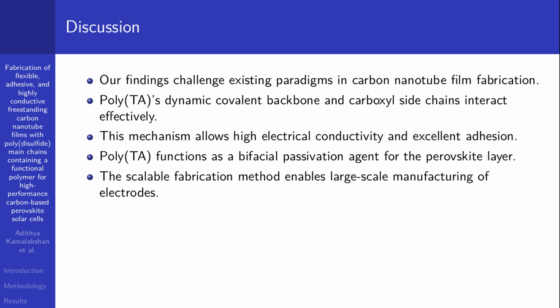synergistically. The hydrophobic backbone facilitates alignment of the carbon nanotubes, while the carboxyl groups provide strong non-covalent binding through interactions like hydrogen bonding, leading to a highly ordered, densely packed, and continuous conductive network. This mechanism allows for high electrical conductivity and excellent adhesion without introducing significant defects or resistance, thereby challenging the notion that polymer integration inherently degrades carbon nanotube film performance. Furthermore, poly-TA's role extends beyond a mere binder. It functions as a bifacial passivation agent for the perovskite layer, enhancing charge extraction and device stability.